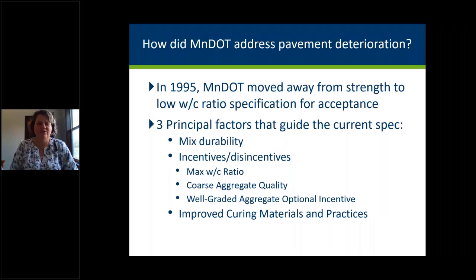So when I say we, it was not me, it was others before me who started to develop these kinds of specs and concepts. So in 1995, MnDOT moved away from the strength concept to a low water cement ratio specification for acceptance. And so that veers, I would say, quite a bit from what a lot of other states do. Many states have water cement limits. However, they still focus on using strength as one of the primary acceptance modes. MnDOT does not do that.